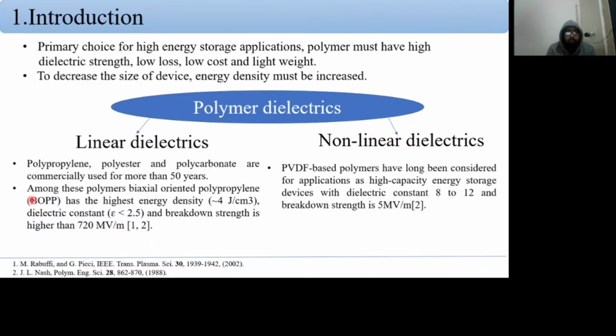So we have two types of polymer dielectric: linear dielectric and non-linear dielectric. Linear dielectrics are those materials which have a polarization versus electric field plot as linear. Here we have various polymers like polypropylene, polyester, and polycarbonate, which are commercially being used for more than 50 years. Among these polymers, we have BOPP, biaxially oriented polypropylene, which has high energy density compared to other polymers, and it has a very low dielectric constant.